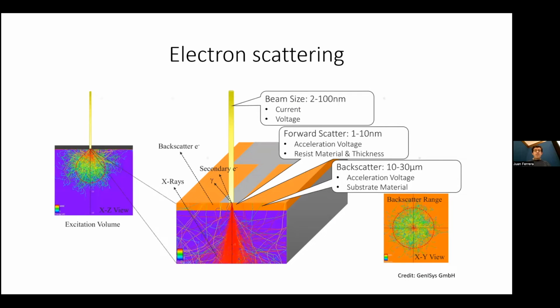So the 10th micron line has pretty much disappeared. All you have is a little knob here. The line has disappeared from here, and the whole thing has turned into a block here, and the line has disappeared from here. And you can also see that there is some rounding of the corners. So what happened? What happened is that when you use an e-beam to write something, you have to deal with electron scattering.